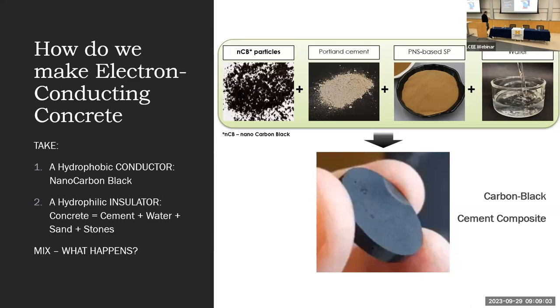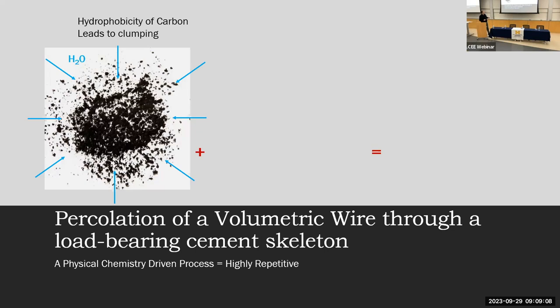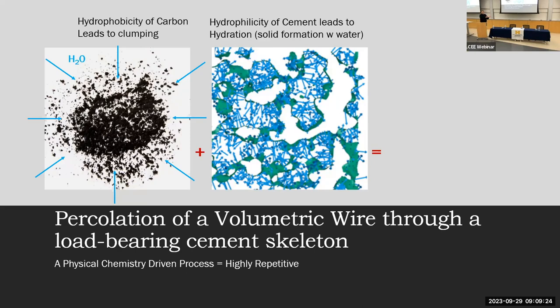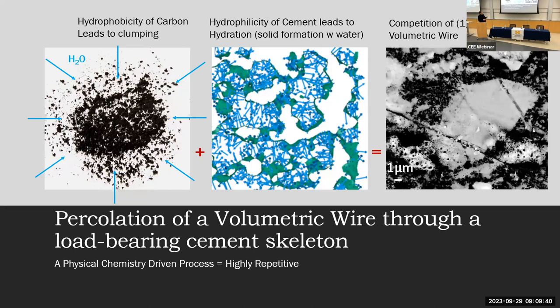In fact, when you put carbon black as a hydrophobic material in water, it clumps. It's held together by the forces of water, and it clumps. So nothing happens with this material. In return, when you add cement to it, which is hydrophilic, consuming in the course of hydration the same water in the alkaline environment of concrete, then you have this volumetric wire permeating a load-bearing cement-based matrix. Because it's a chemically driven process, everyone can do it. You just need to mix up carbon black with cement and water in order to obtain this material.